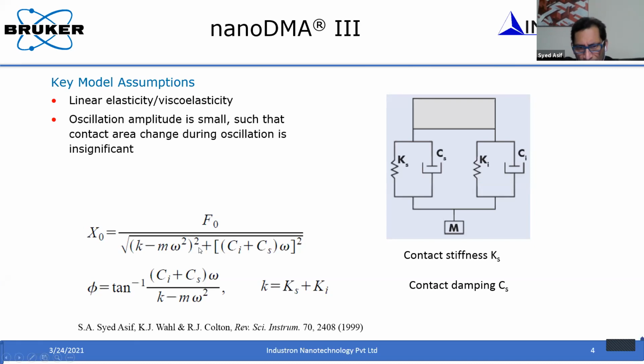And then there is damping, the damping within the transducer, and also damping when you make contact with the sample. So these parameters, at least if you know them for the transducer, then you can calculate for the material. Okay, so this is a very simple mathematical model, simple harmonic motion, that you can use. If you know the force you apply, you can calculate the displacement, and you can also measure this displacement from the lock-in amplifier. And you can also measure the phase shift between the force and the displacement. That is what I'm showing over here.